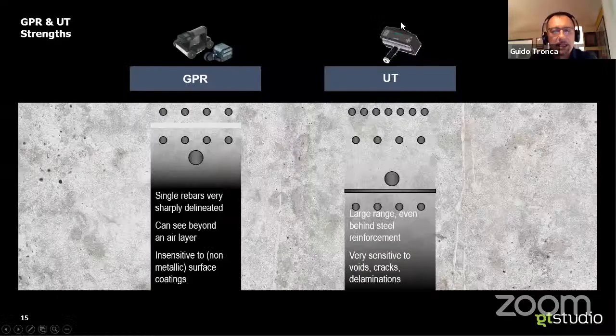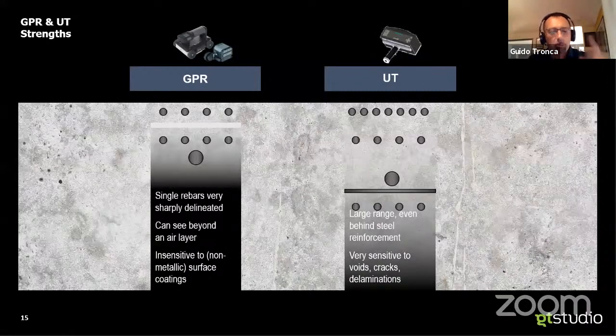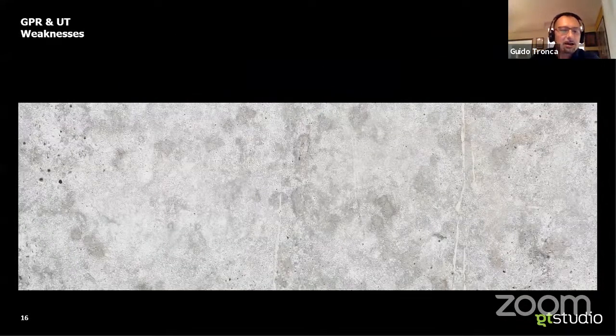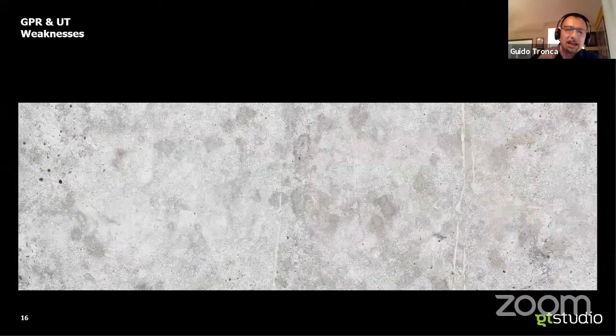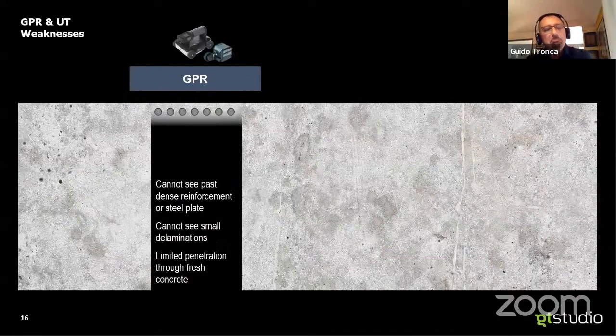This guy here will be the real flaw detector for concrete, in that it will point out with a very strong reflection the slightest interface, such as a void, mold, delamination, cold joint, you name it. Well, echometric techniques: the general rule is whatever you see the best will make you blind below.